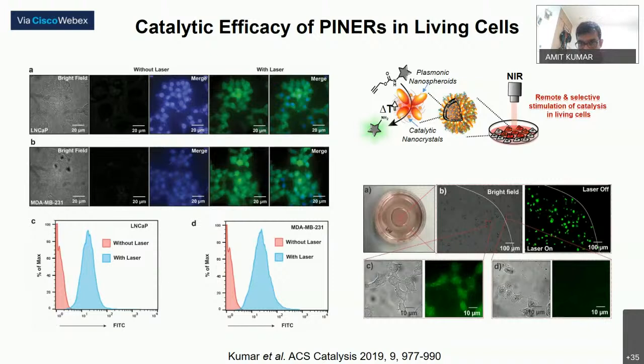So this figure shows that the reaction can be selectively activated in the selected population of the cells. So by shining the laser on the selected part, the cell population can activate the fluorophore in the selected region. So it shows the local selectivity of this chemistry.